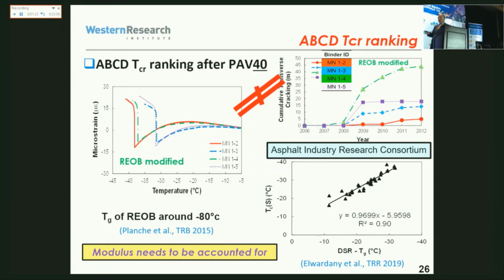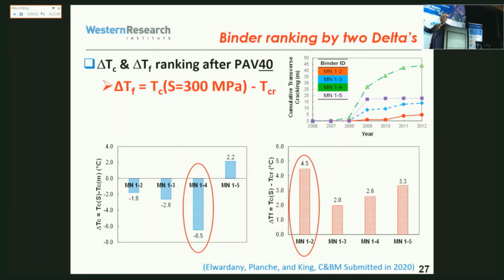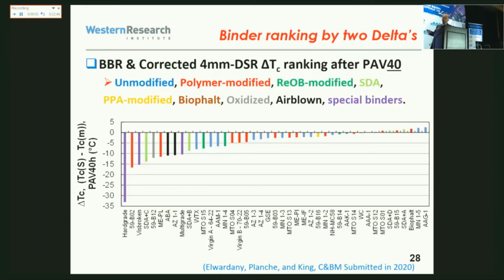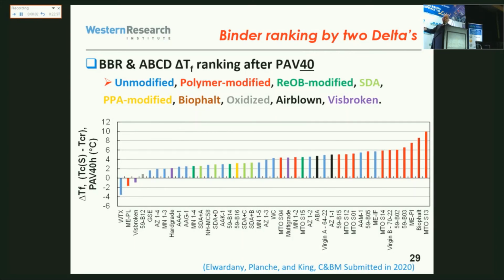So we came up with a new parameter, which is another delta. It's not delta TC; we call it delta TF, F for failure. That's the critical temperature of S, measured by BBR, minus the critical temperature coming from the ABCD test. When we do that, we get the good ranking for MN1-4, and we give the right credit to the polymer modified asphalt. Then we ranked all the binders from the study, and this is the delta TC ranking, with polymer modified in many places. And this is the delta TF, and all of a sudden, most of the polymer modified binders are showing very good results. They are at the right place where we expect them to perform.